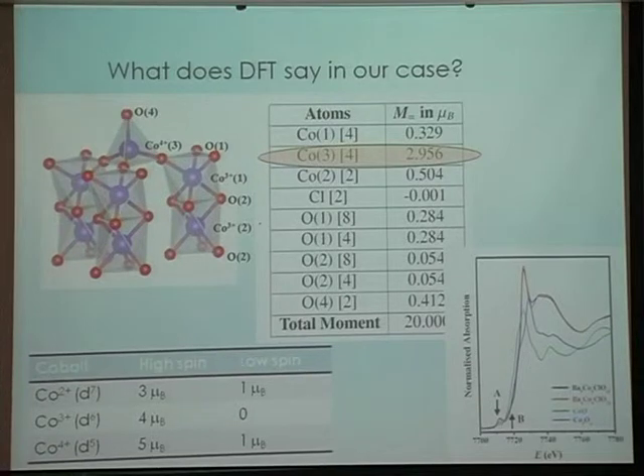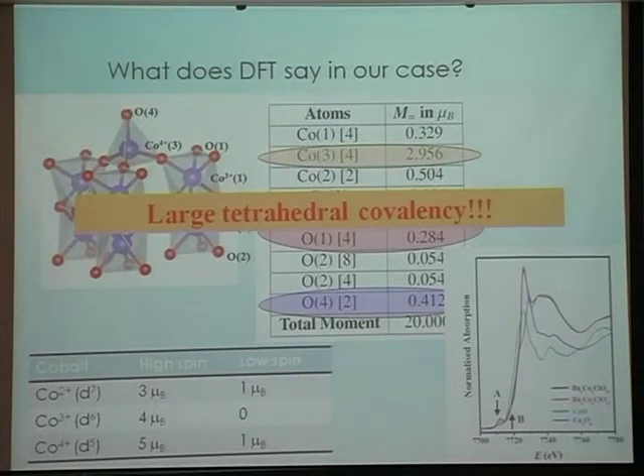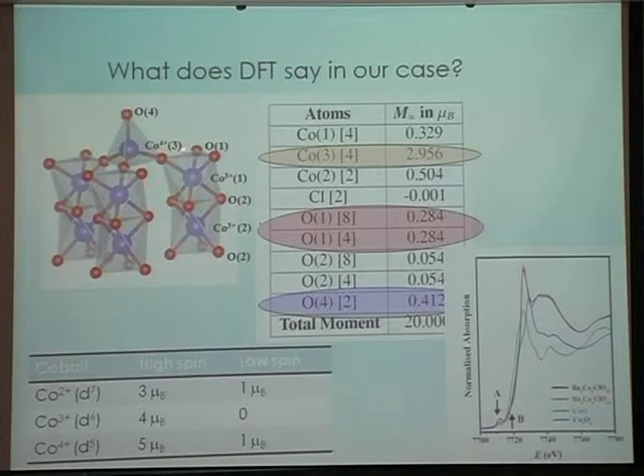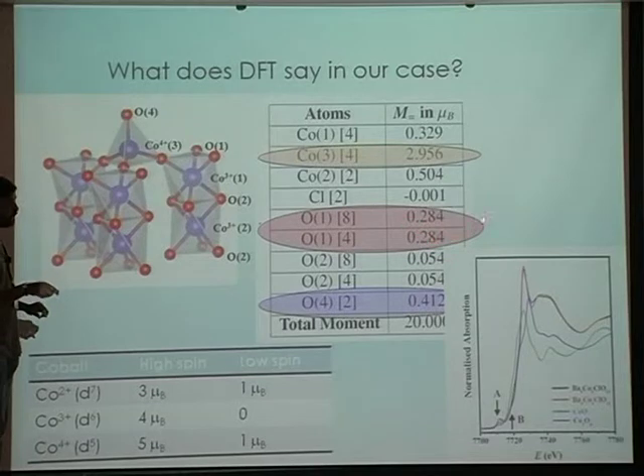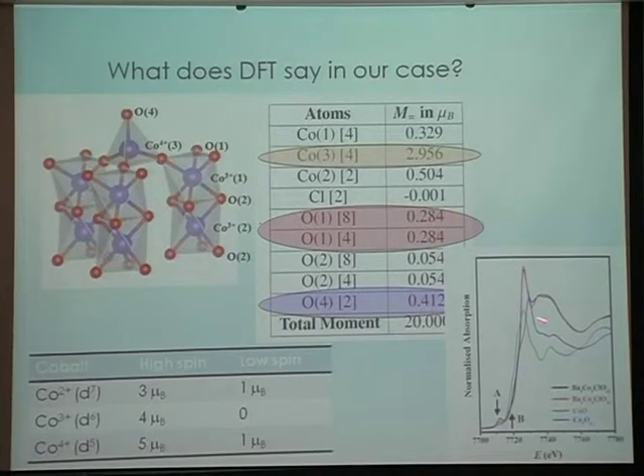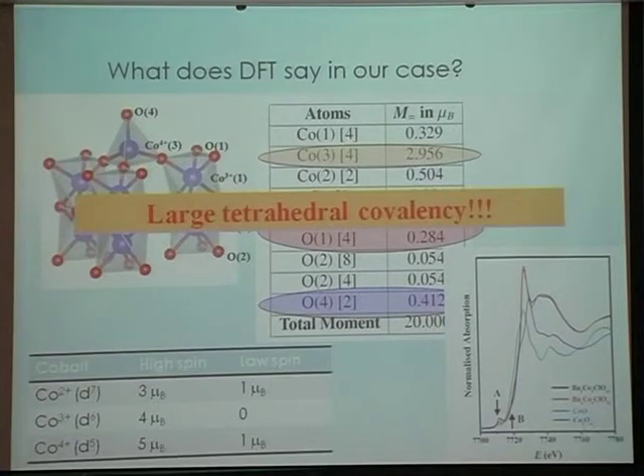But if this happens, like in the permanganate case, what do you expect is these oxygens to be having lots of holes, and that's precisely what happens. Oxygens developed a lot of holes, 0.3, 0.4, quite large for an oxygen, very, very large for an oxygen. So what I conclude from here is that in these compounds, this particular tetrahedra is doing something strange where these oxygens are accommodating lots of holes, and this cobalt is getting reduced from 4 plus to 2 plus.